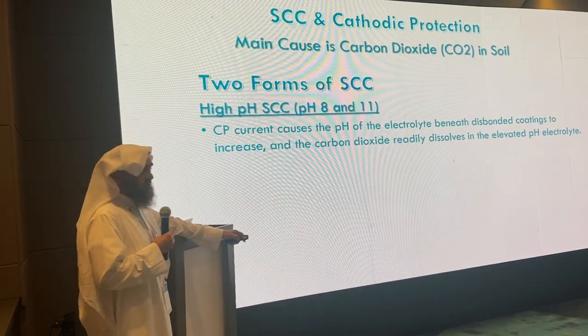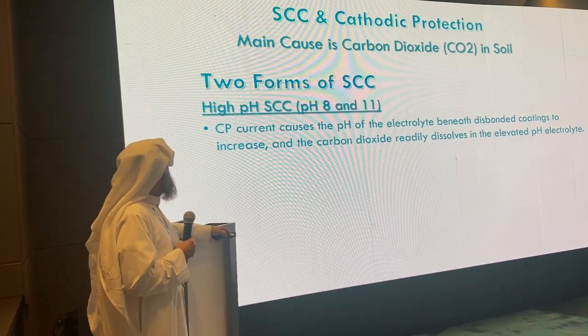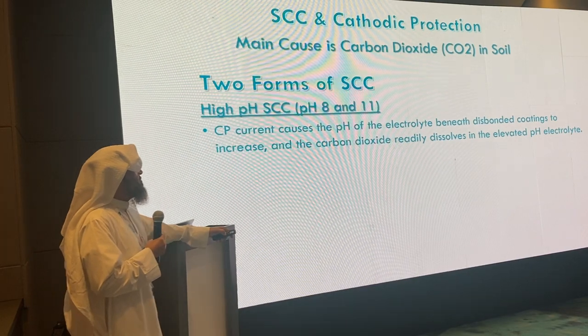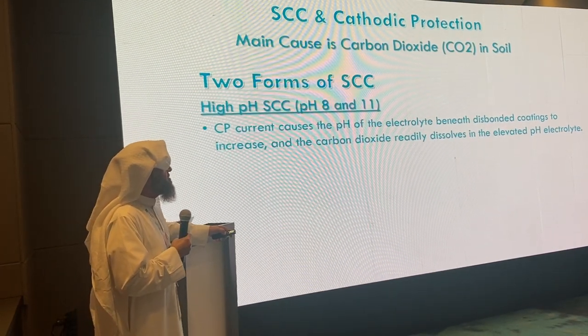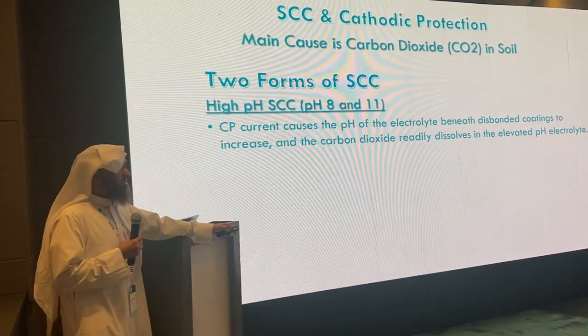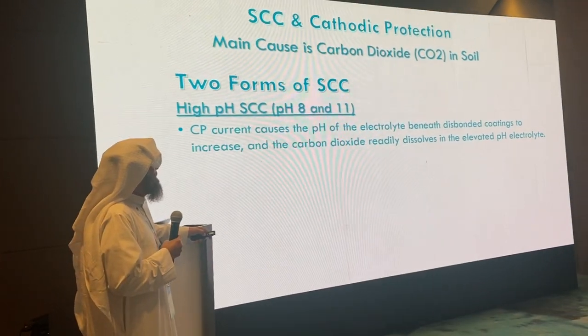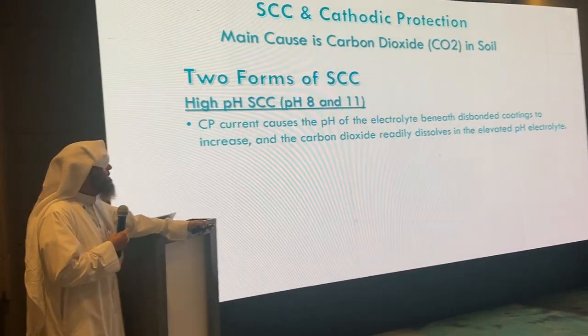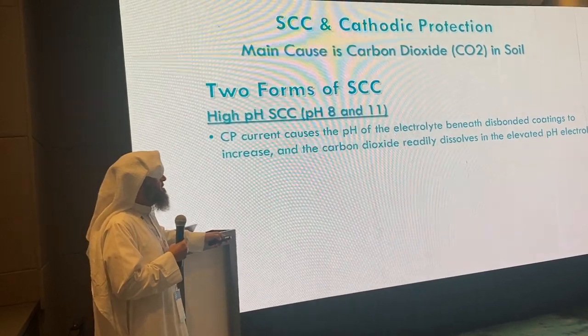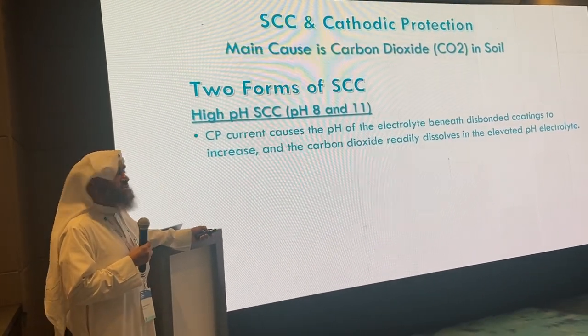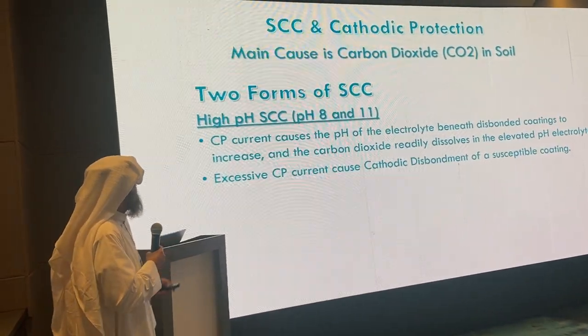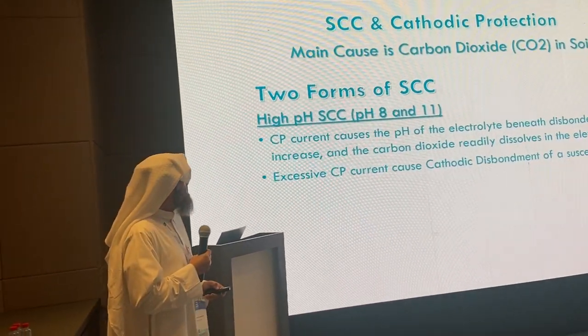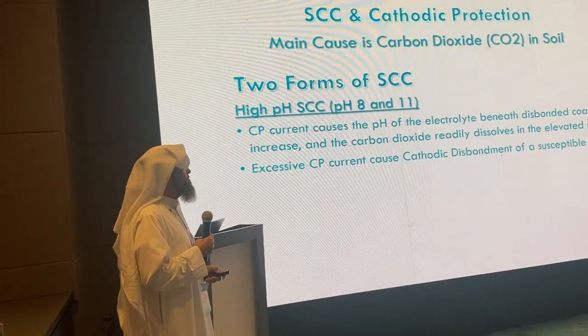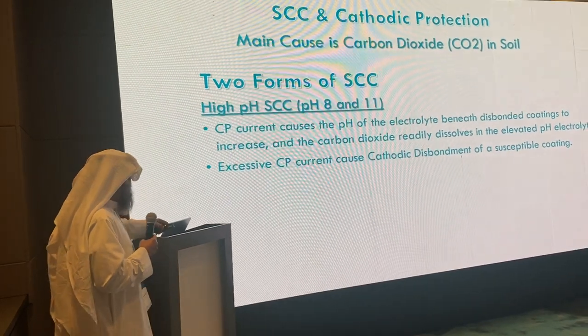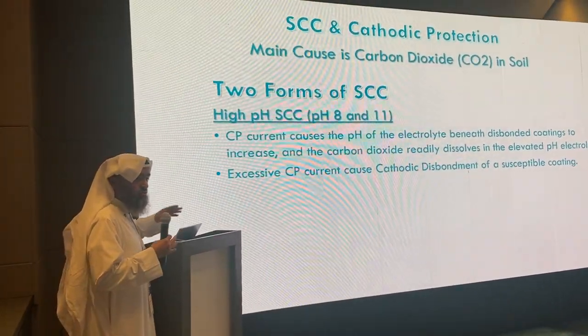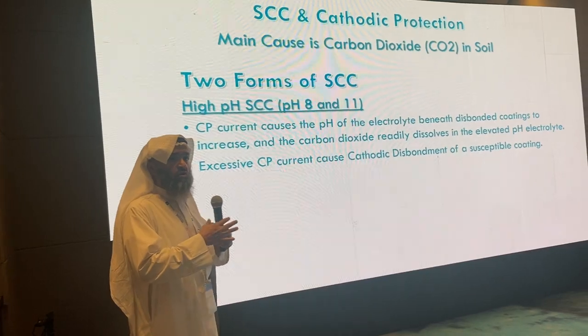And in this type of failure, the CP current causes the pH of the electrolyte beneath the disbonded coating to increase. This increase in pH makes the carbon dioxide readily dissolve on the substrate surface. Also, excessive CP current causes cathodic disbondment, making susceptible coating disbond.